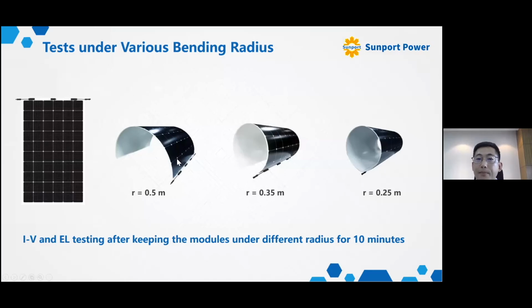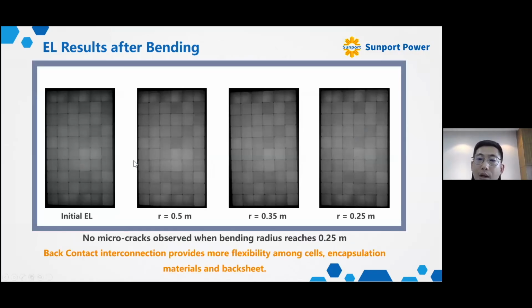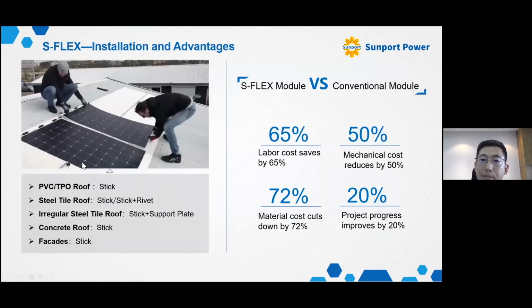And this is the extreme testing of flexible modules by bending them with different radii and testing again. As a result, no micro cracks were observed in all scenarios, and no power degradation was observed after bending them. This result shows you how good the flexibility and the reliability are, even though you will never use the module bent in a circle like this. And there are various mounting approaches to install them, as listed here.